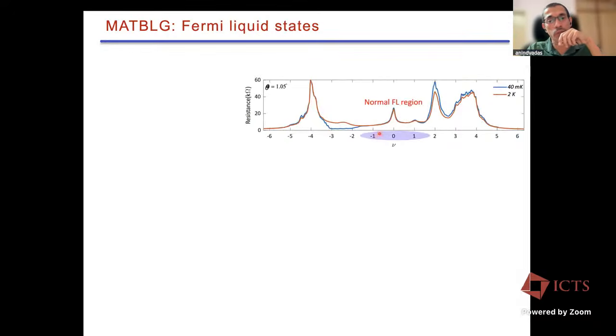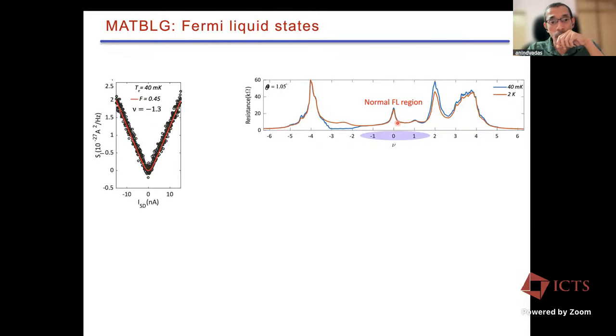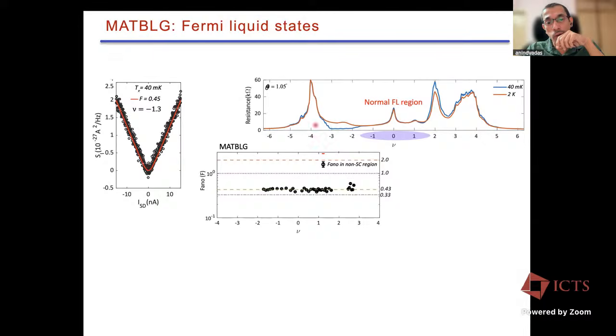If you start doing the noise measurement in the Fermi liquid regime, this is what the noise spectrum looks like. If you try to get the slope, the Fano factor turns out to be 0.45. And not only at a single point, we looked throughout this normal Fermi liquid regime of the twisted bilayer, and the Fano factor is 0.43, just to make sure, as a benchmark, that our systems are working really fantastic.